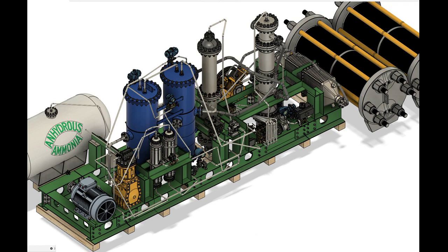Unfortunately, this higher density came at a cost, as the law of compensation almost always imposes. The major disadvantage of Claude's reactor was that it featured a significantly shorter catalyst life. While Haber-Bosch catalysts at the time lasted 2 years, Claude's lasted only 3 months.